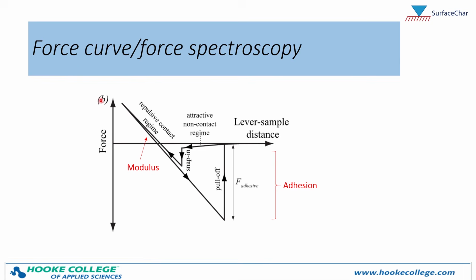All right, so let's go back and look at force curves, the static force curves, now in detail. So we went over the approach, the snap-in, then the repulsive contact, and then on the way out, we get stuck in this adhesive dip, and then we pull out. The two kinds of information that I'm going to focus on today that we can extract from our force curves are first the adhesion energy, which we get from this part of the force curve, which is a pull-off force, and the stiffness or modulus information that we're going to get from this repulsive contact region, part of our static force curve.